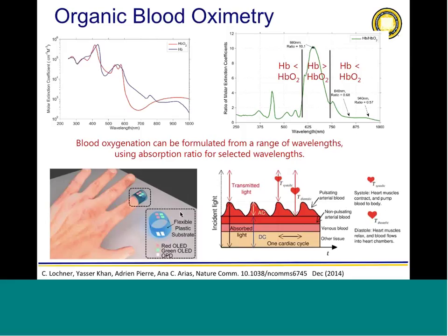And the reason you can calculate blood oxygenation out of this is that if you look at the molar extinction coefficient in the blood, there is a difference in the absorption between the venous blood and the oxygenated blood. This difference in absorption is quite substantial around the red, quite big around the infrared, but there are also differences in other areas. If you look at the ratio between the absorption of the oxygenated blood and the venous blood, you can see that there are several areas where you could pick up that difference.